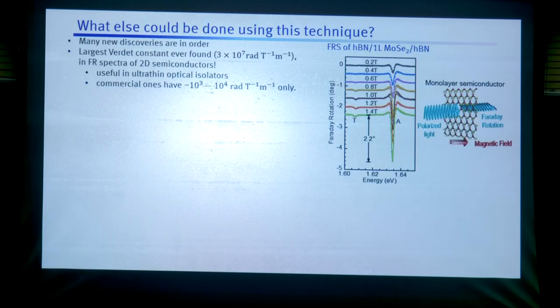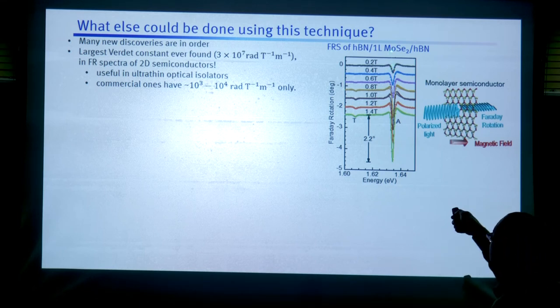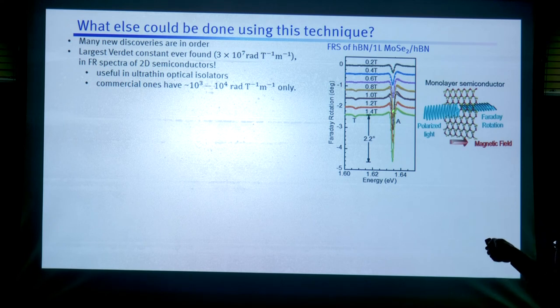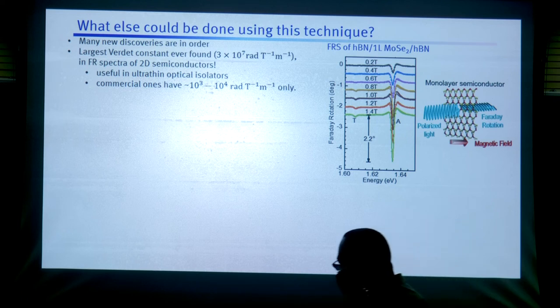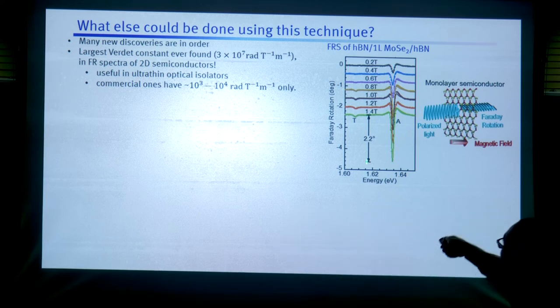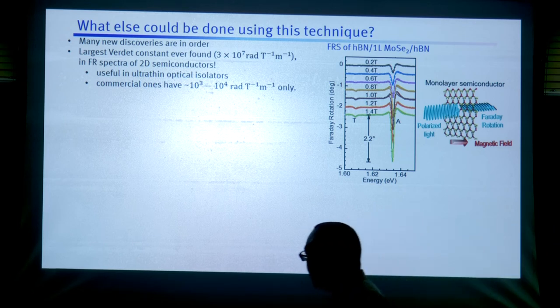What else can be done using this technique? Well, what we have found recently is that, for example, in this MoSe2, the rotation is so large just through this single layer of material. This layer is just single layer thick, and it can rotate light by 2.2 degrees at 1.4 Tesla. Now, this is huge. I want to tell you how.